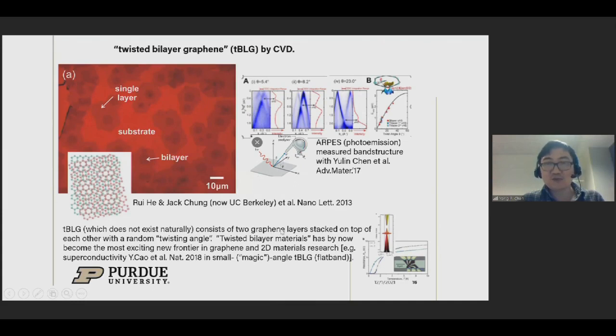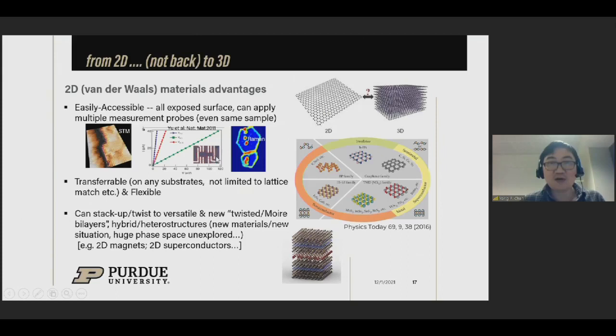I should mention a few years later, there was a striking discovery made by people, for example, Pablo's group at MIT, that showed in this twisted bilayer graphene at some magic small angles, it can become superconducting. So that's today a very, very hot field, not just twisted bilayer graphene, but many other materials. In fact,